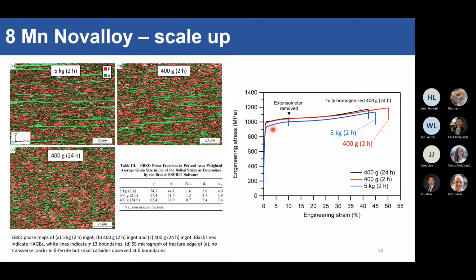But you've got a slight drop in strength in the big ingot, and that's because you've got a much larger delta ferrite grain size compared to the rest of the matrix, which is a very fine grain itself. So this is great. We've actually proved that you can homogenize medium manganese steels, and take note that this is a fairly highly alloyed medium manganese steel. So if you dial back the aluminium and silicon contents, you can actually remove delta ferrite in the final microstructure totally. And that's great news for medium manganese steel, on the industrialization and commercialization front.